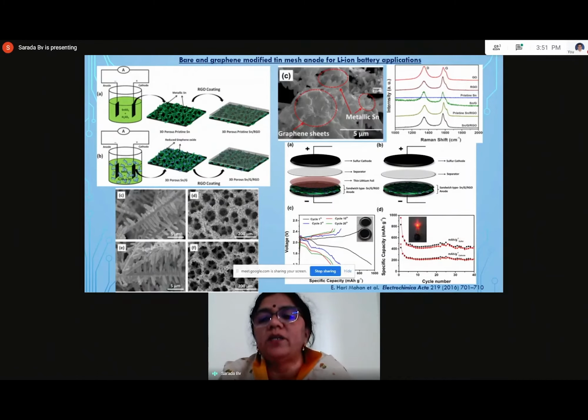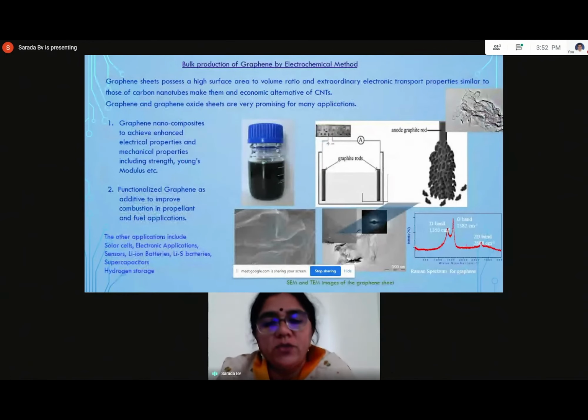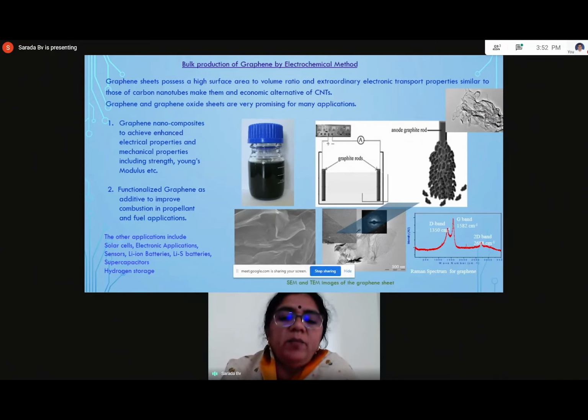And we have used Raman spectroscopy to confirm that the exfoliation has formed graphene, and the graphene is also made in-house. We have not taken the commercial one. You can see over here, again by the electrochemical exfoliation method, we could make a few grams of graphene to be put into the electrolyte, and it shows the graphene structure with the 2D band at 2688, that is below 2700, which shows that it is a graphene structure with a small number of layers. And also from the TEM and FESEM images, you can see that it is good quality graphene.